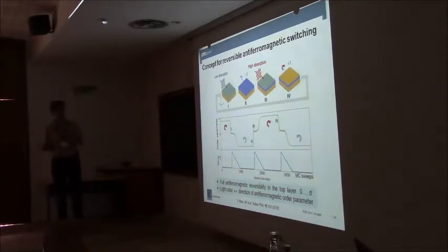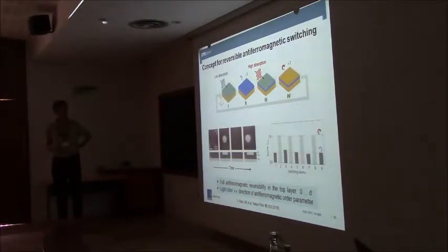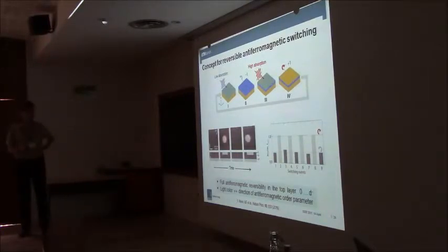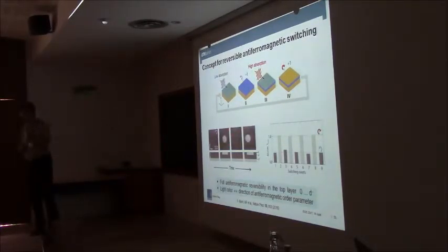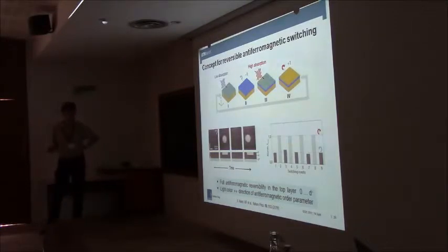It's great, good, but of course you want to do it in real life. And in real life it looks like this. So switch black to white, back to black, back to white, and so on. 100 times, 200 times, no problem. You don't switch the entire sample, but you always switch this region in the sample continuously between dark and bright, or left-handed, right-handed antiferromagnetism, or up polarization, down polarization. And the imaging is always with second harmonic because it can distinguish these two domain states.